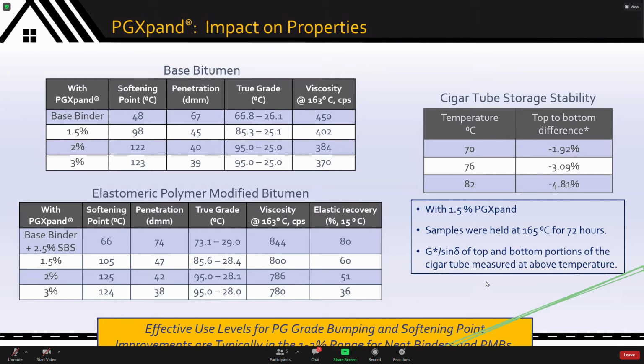Here is the cigar tube storage stability of the material. In this test, your PGXpand dosed bitumen is maintained at 165 for 72 hours. The top third and the bottom third is cut off. And here we have measured G-star sine delta using DSR rheometry. But you could also measure softening point, you could measure phase angle, you could measure penetration. In this case, looking at G-star over sine delta, a rheometric measurement across 3 different temperatures, you're seeing less than a 5% variation in properties between the top and the bottom. So it is exceptionally storage stable while it is providing these kinds of property improvements.